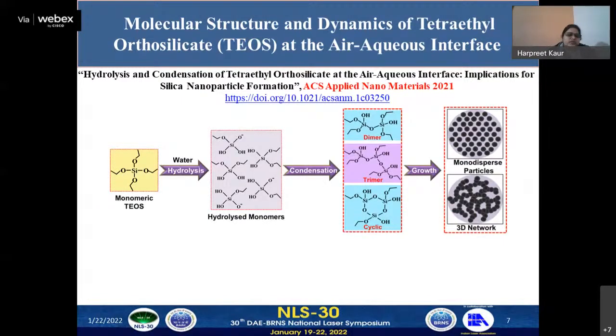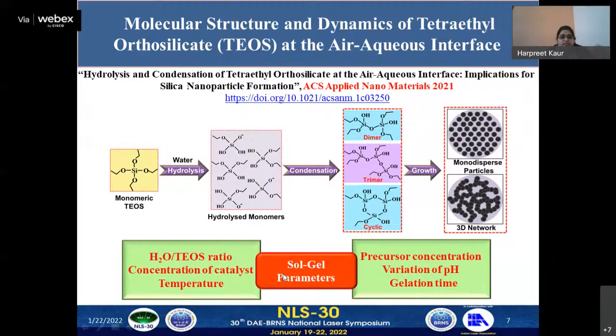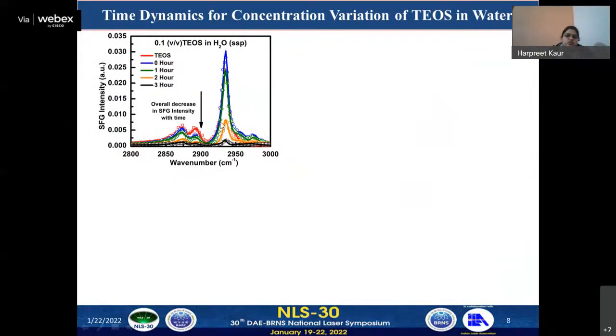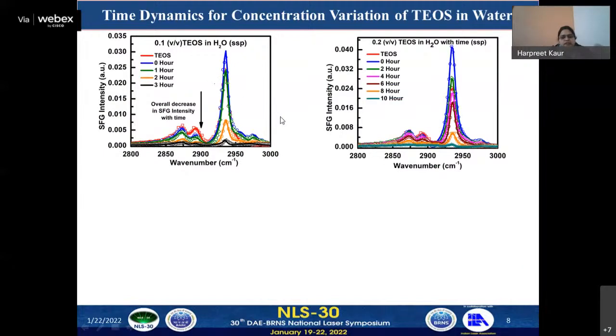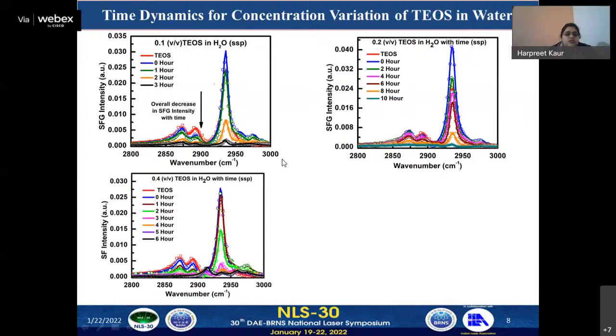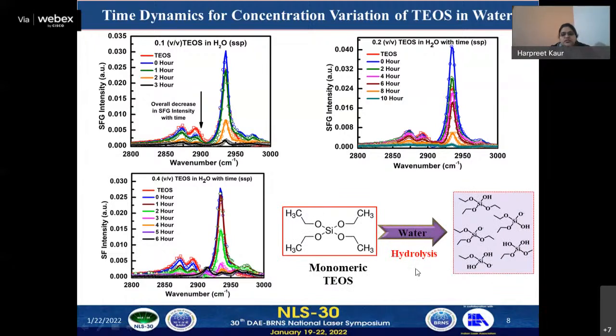TEOS is used as a precursor in the sol-gel mechanism to form silica nanoparticles. There are many parameters in the sol-gel mechanism which have to be known, but our study is mainly focused on controlling the concentration parameter and also the variation of pH of the aqueous medium. The SFG spectrum is obtained for varying concentrations of TEOS in aqueous medium, from which we observe an overall decrease in the SFG intensity with time. We have also observed similar changes at higher concentrations of TEOS. From this, we observe the CH moieties, which are the signal of the CH vibration modes, and these CH moieties get eliminated over time, which is possibly due to the hydrolysis of TEOS.